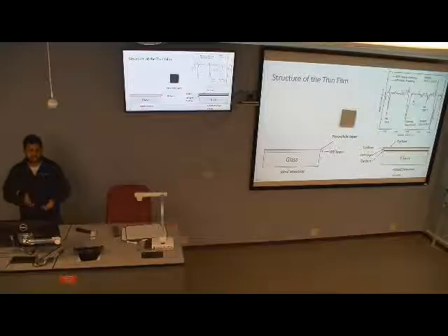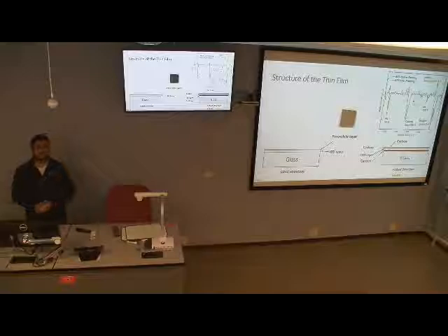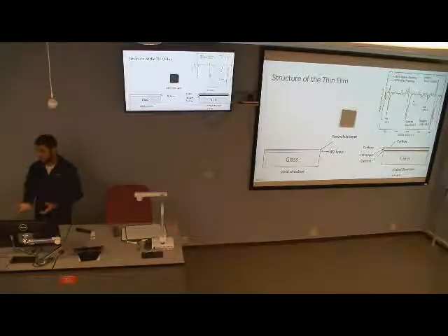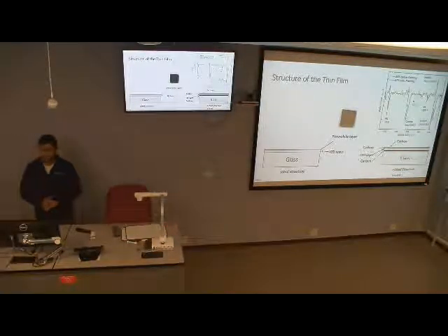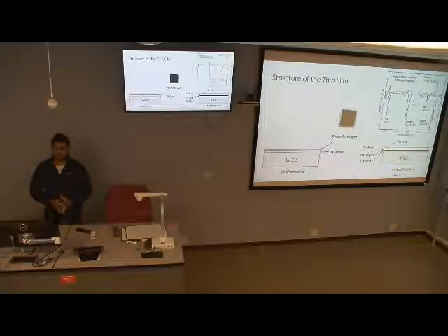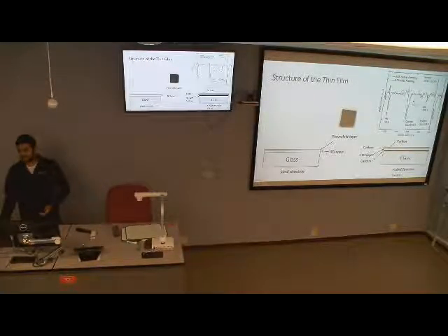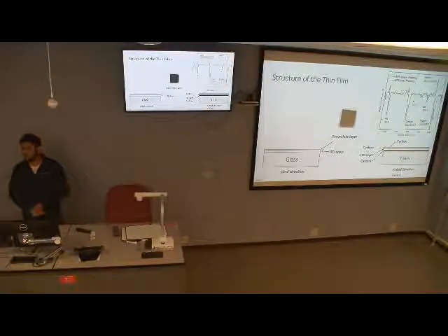We also saw, when we did the thermal desorption studies and stability tests, a huge amount of carbon dioxide and water desorbing from the surface. This is most likely due to the adsorbed carbon dioxide and water. There can also be some residual carbon deposited on the surface. So even though we need an ideal surface without any impurity layers, we unfortunately have some impurity layers on this perovskite film.